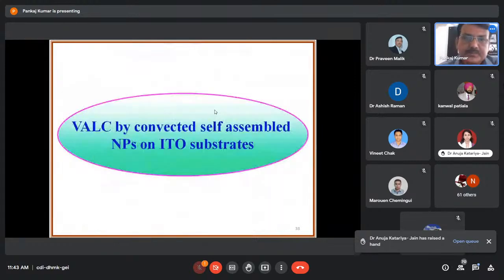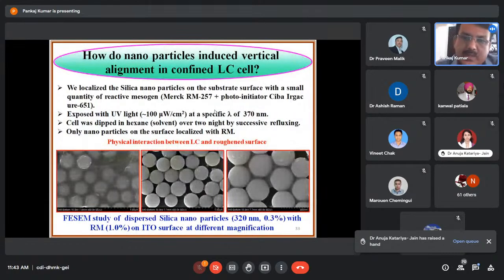Then again, I would like to communicate here that the nanoparticles are going to the surface, and physical interaction between liquid crystal as well as the roughened surface is giving the vertical alignment of the liquid crystals. So this experiment was done for confirmation of whether these nanoparticles are in the bulk liquid crystal materials, or these nanoparticles are going on the surface. So most of the nanoparticles are going on the surface, and they are modifying the surface. That's why they are giving the